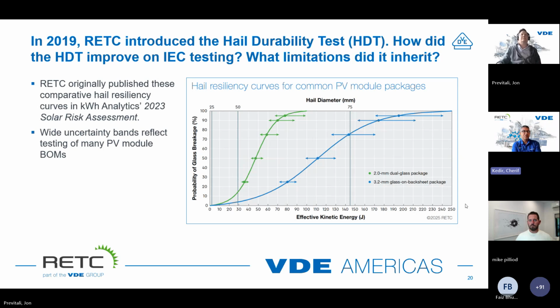The revelation there, working with our sister company, as John Peritelli noted, the VDEA team and many of our partners, was realizing that this is a probabilistic function, not a binary function. What that requires is that we understand the probability of failure, not whether a product fails or passes. And the probability of failure can be reduced or increased depending on the module construction as well as the mitigation strategy. For instance, if a module is sitting flat in an area versus tilted, it changes slightly the probability of failure. At the same time, the construction of the module plays a big role in that probability of failure, regardless of how the module is installed.